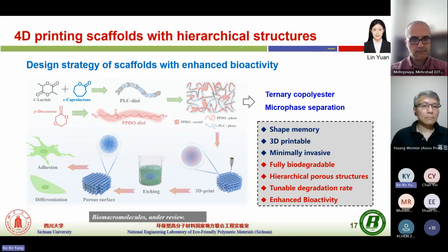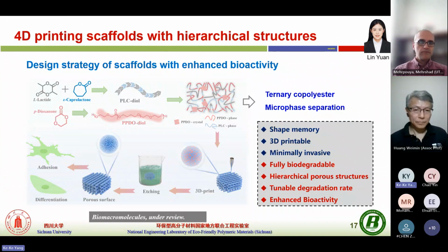The second example here we'll introduce is a 4D printing scaffold with hierarchical structures. In order to create the hierarchical structure on the materials, we first designed ternary copolymers. In the first step, we random copolymerized the lactide and the caprolactone to get a random copolymer with tunable glass transition temperatures near body temperature.